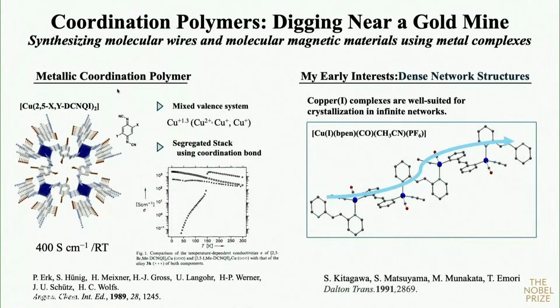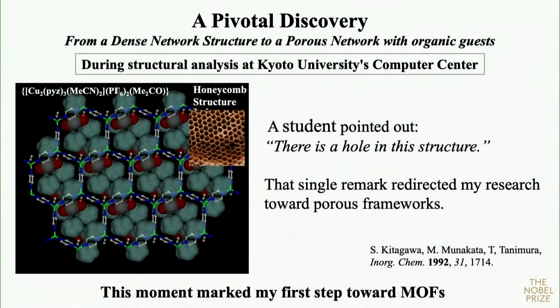I was very interested in this system, and we were interested in the fully densely packed structure because, for the conductivity pathway, the dense structure is good for these properties. However, one day I tried to determine the crystal structure with my students at the Kyoto University Computer Center. The center was so crowded. I had to wait for a long time, for 1 or 2 hours, to analyze this data. In that time, we just analyzed the interpenetrated structure. The student said, there is a hole in this structure. I was so impressed, excited to see, because in the cavities, there are ions and also organic molecules. So this moment marked my first step toward MOF.